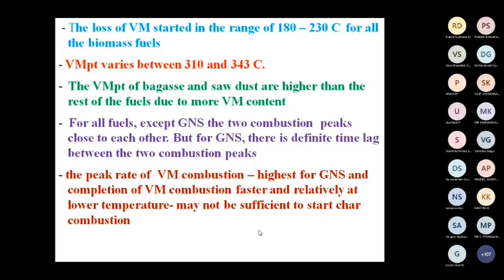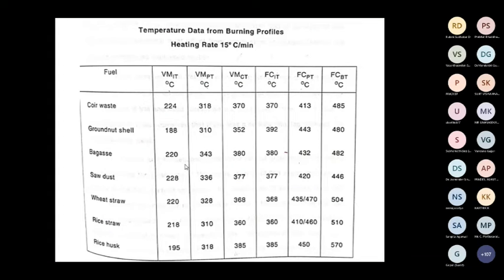The reason is that the peak rate of VM combustion is highest for groundnut shell and the completion of VM combustion is at a faster rate, because you have seen it completes at 350 degrees. Maybe 350 degrees may not be sufficient to initiate fixed carbon combustion, so it has to rise up to around 390 degrees to start initiation. So VM release and combustion for groundnut shell is very fast. That's one of the indications. VM release and combustion is so quick for groundnut shell. That's why there is a time lag.